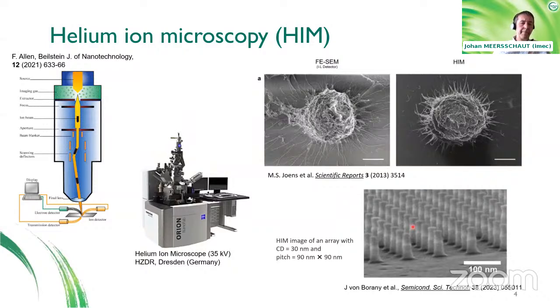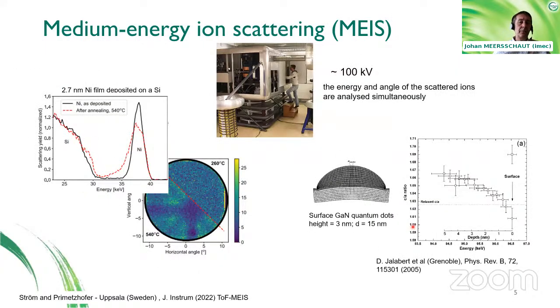Now, this approach is not very much a large infrastructure technique. For that, we need to go to higher energies. And one of the techniques that uses higher energies is medium energy ion scattering. We speak about medium energy ions when the particles have energies between 100 and 400 to 500 kilo electron volt. So for that, you need an accelerator which can go to these voltages. And here you see the picture of an implanter-like accelerator, which is hosted in Uppsala in Sweden at the Angström laboratory, where particles can be generated at an ion source inside this enclosure, which can be brought up to 100 kilovolts.